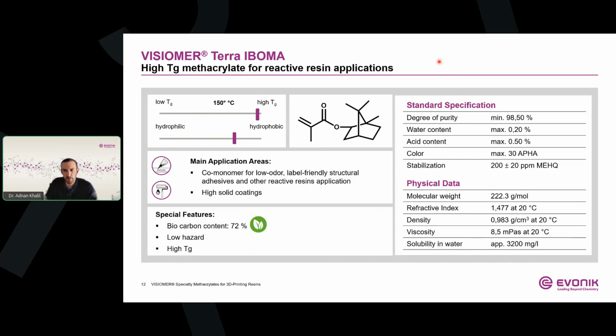Next, I would like to have a closer look at another monofunctional monomer of our portfolio. This is the VISIOMER Terra Iboma. The Terra Iboma is, as I also mentioned in the beginning, a high Tg methacrylate with approximately 72% biocarbon content and a Tg value of around 150 degrees C. So thanks to this rigid isobornyl structure, the Terra Iboma is highly effective in increasing stiffness, dimensional stability, and heat resistance in photopolymer networks.